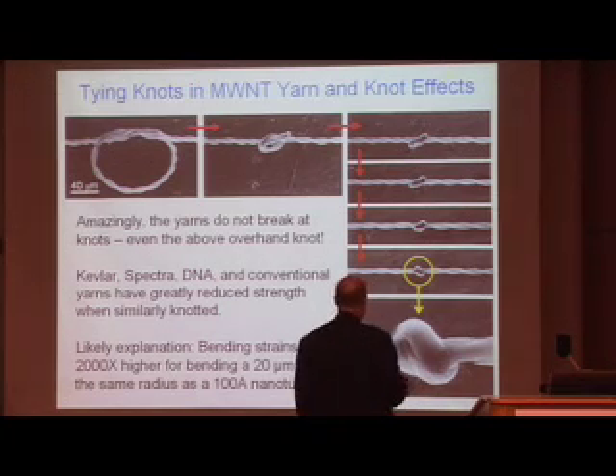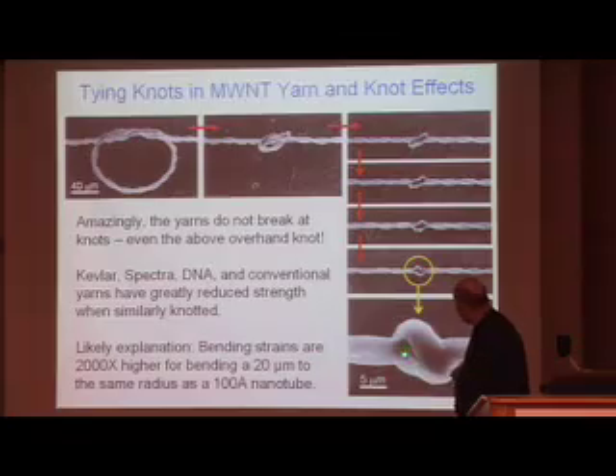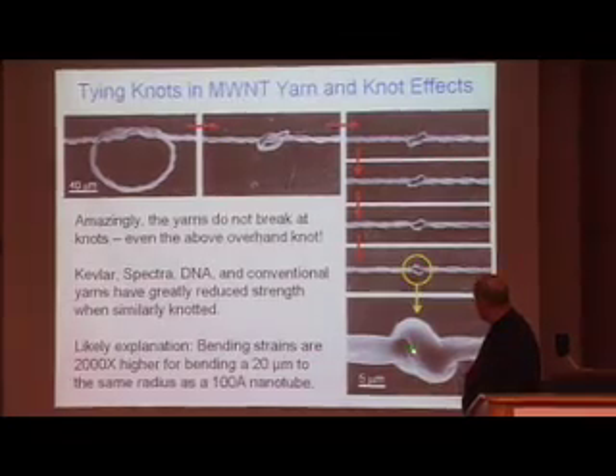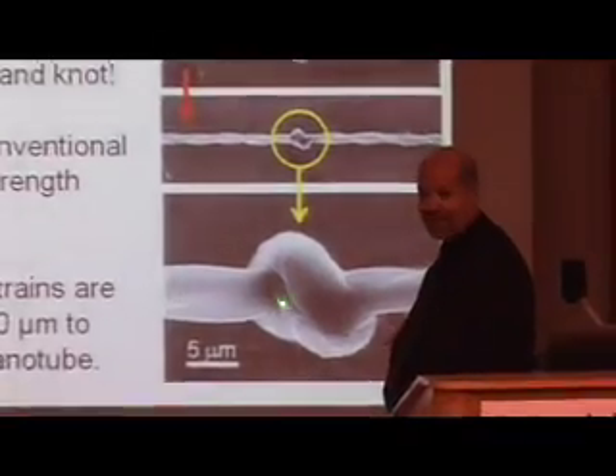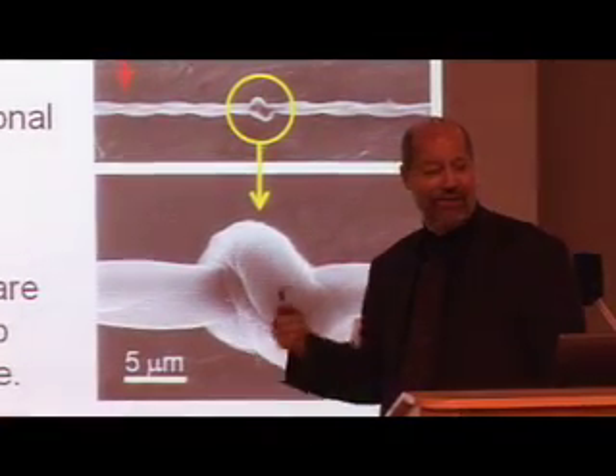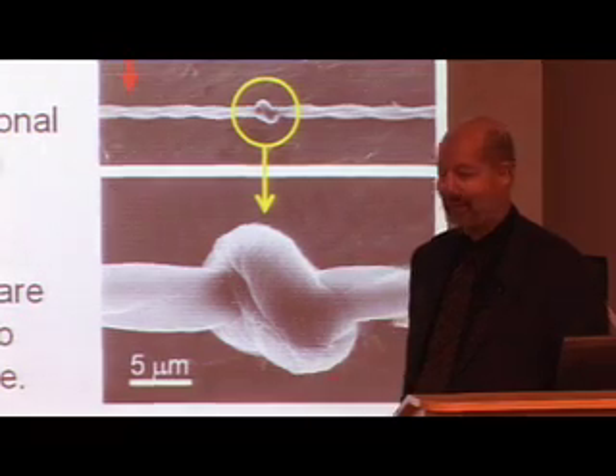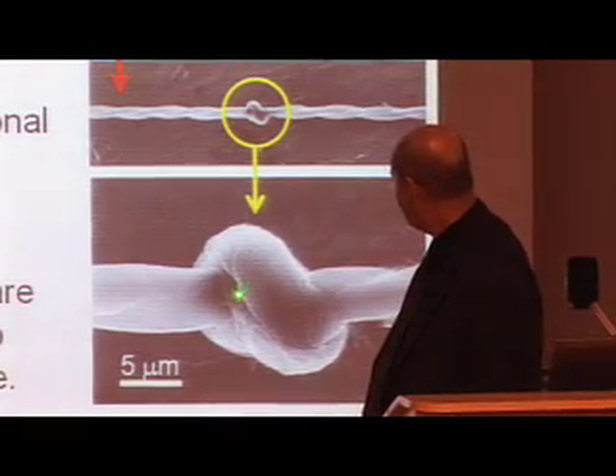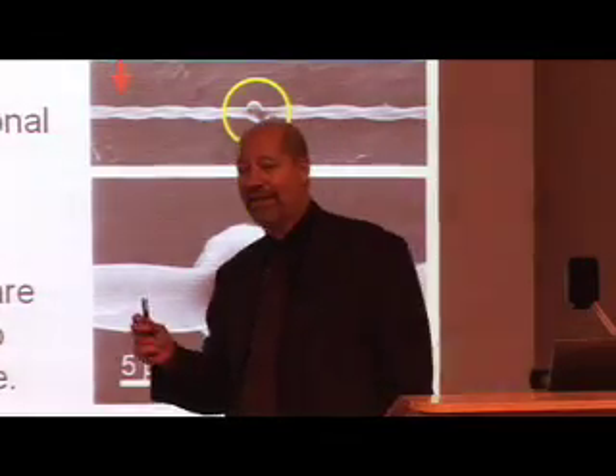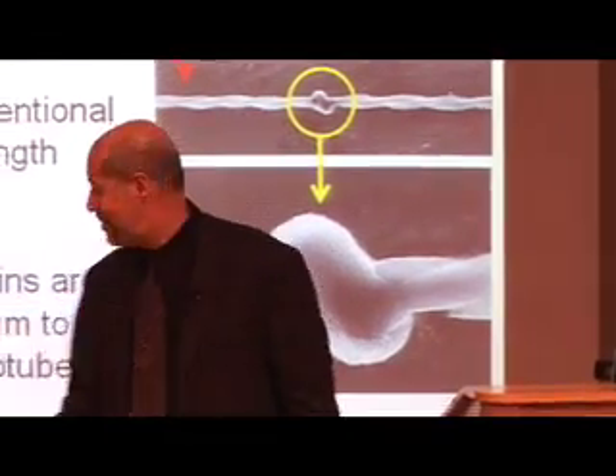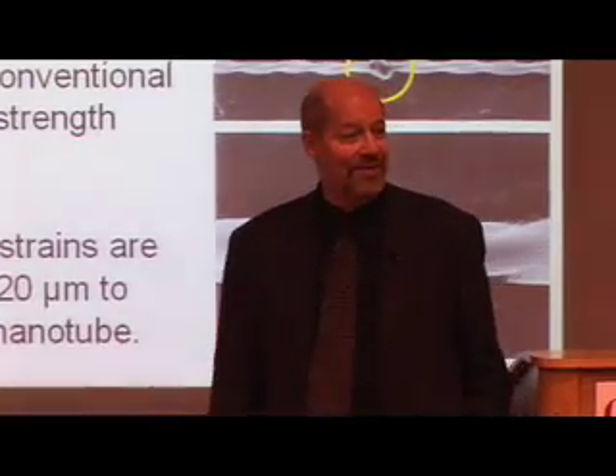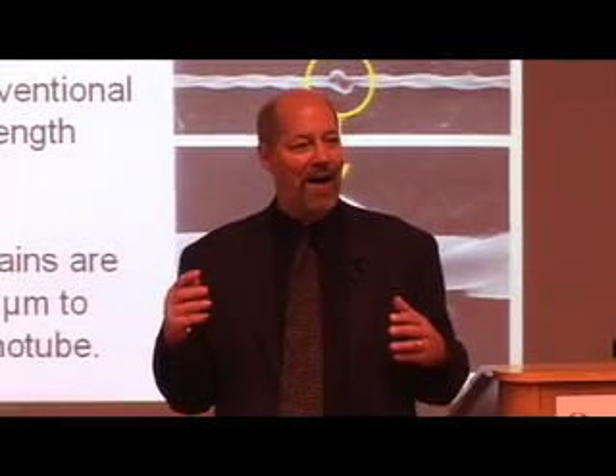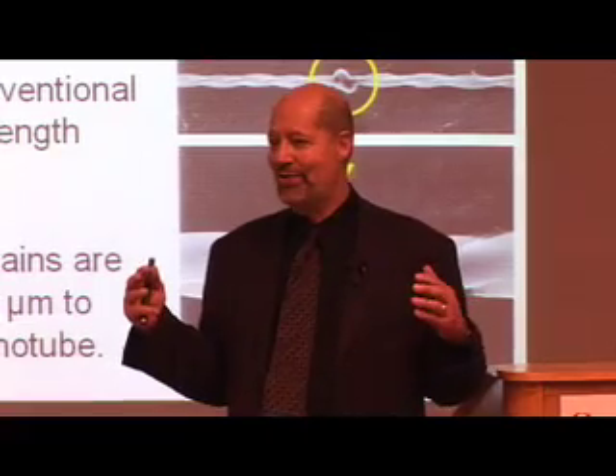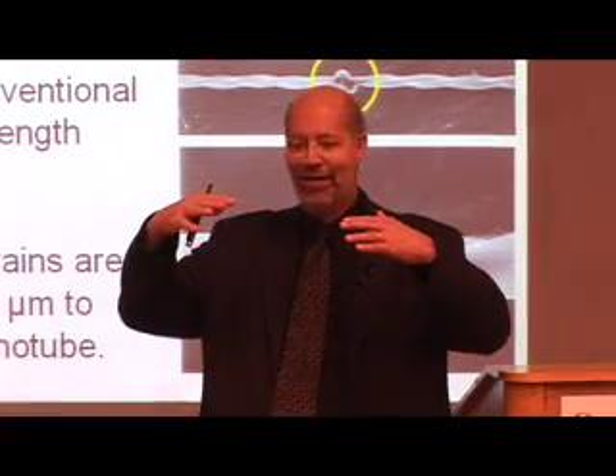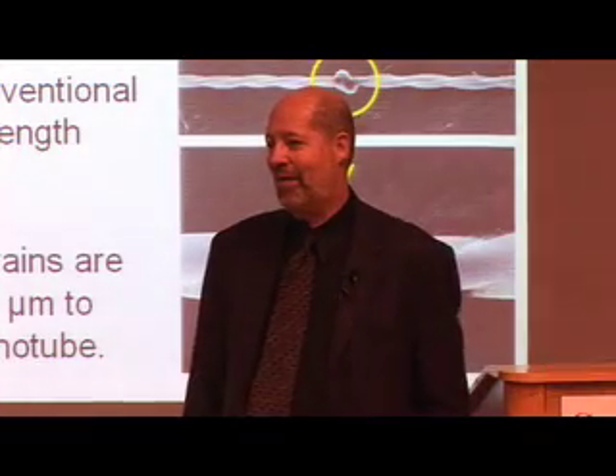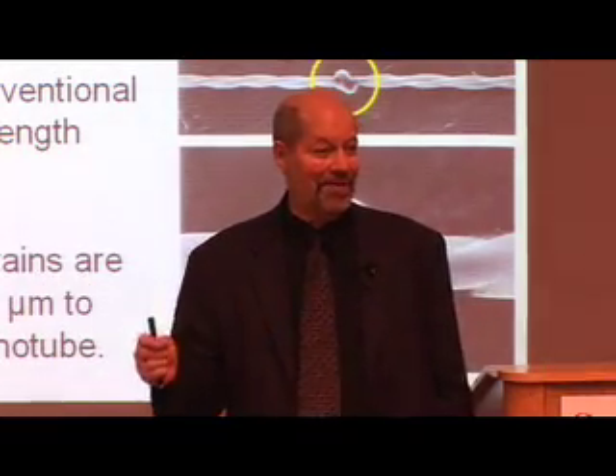Now, if you look at this knotted yarn, you can see the radius of this knotted yarn is about 5 microns. That 5 microns radius, even though it's very small, about 1/20th the diameter of a human hair, is giant compared to the diameter of the individual carbon nanotubes that are in this yarn, which are only about 20 nanometers. So the individual nanofiber in the yarn doesn't even know it's knotted. It's deviating such a small degree from a straight line compared to its diameter.